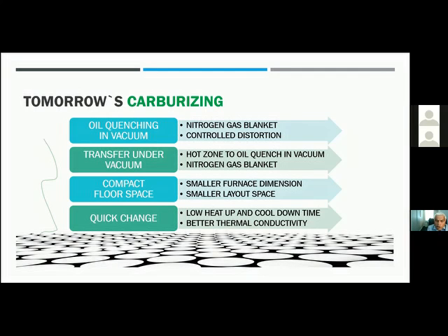But if you use oil quenching, you don't have to touch anything with your steel. You can still get your core hardness and surface hardness, mostly surface hardness, that you would need. This is done using nitrogen gas as a blanket material so that there is absolutely no possibility of oxygen or air infiltrating inside.